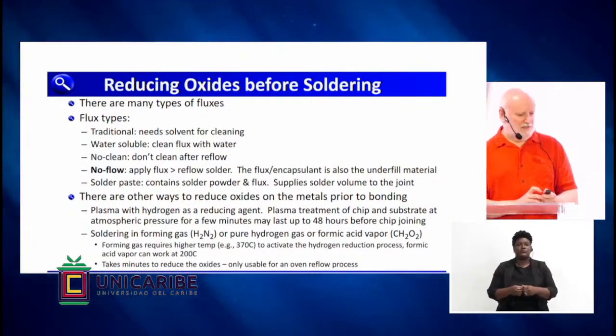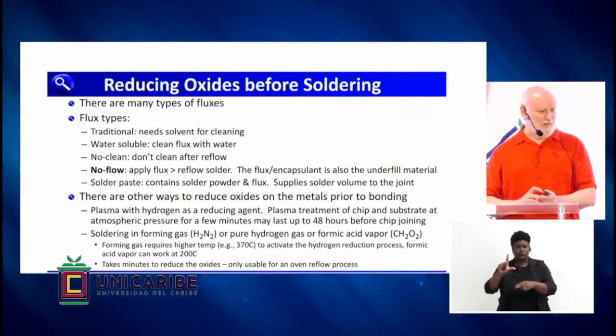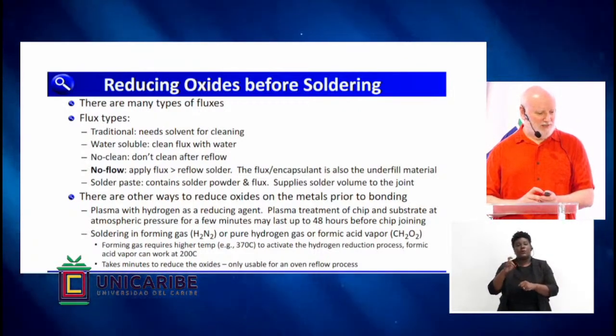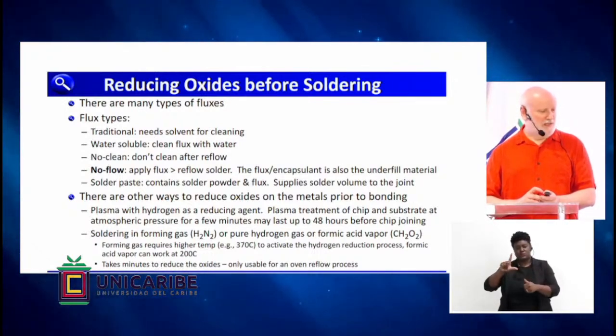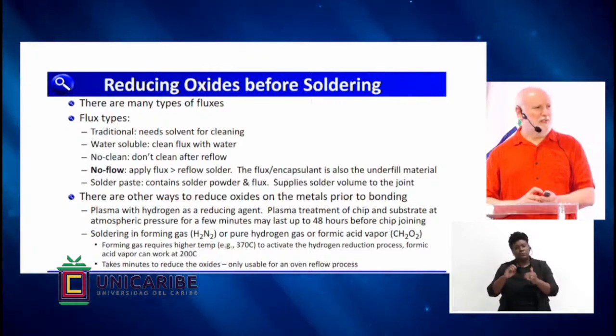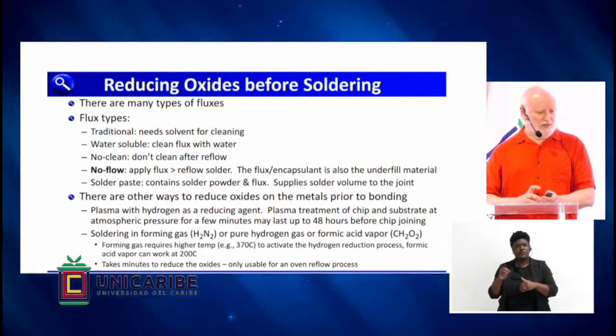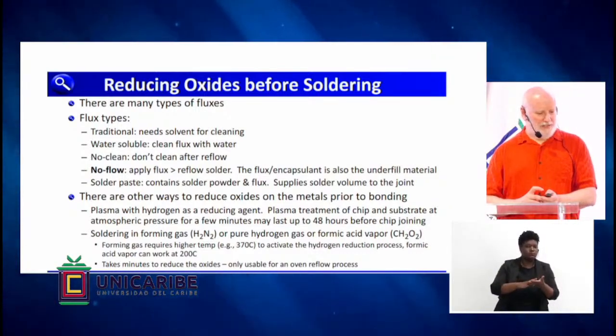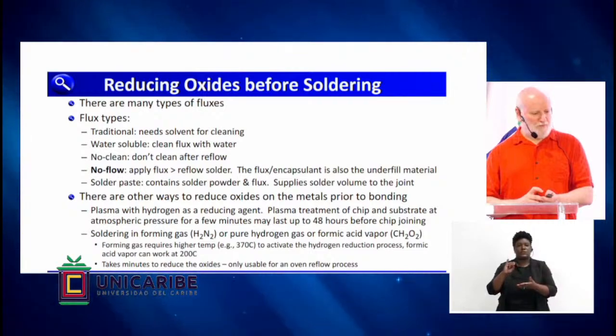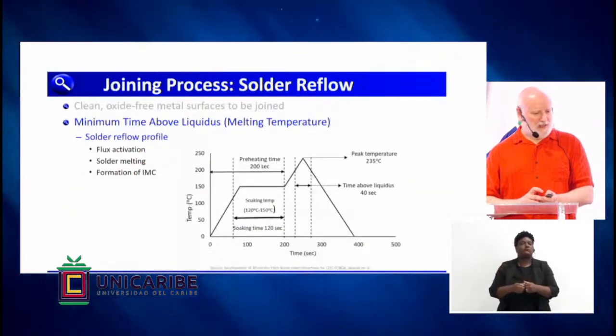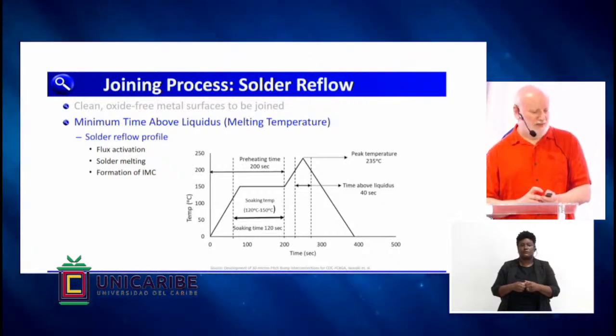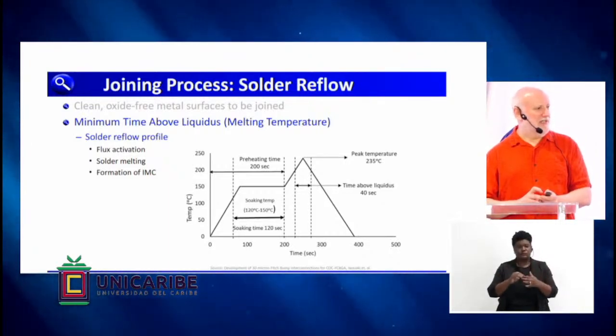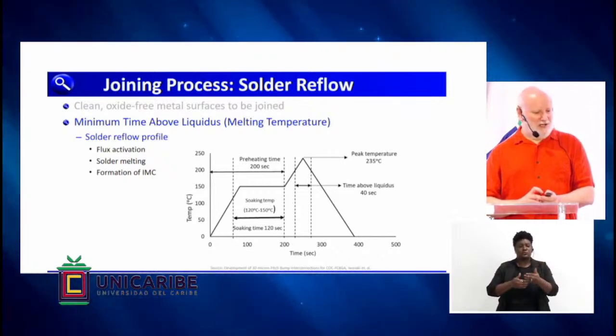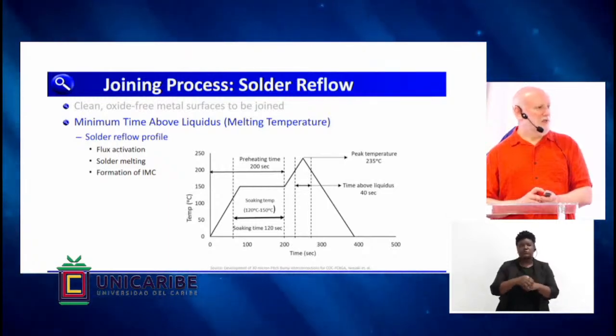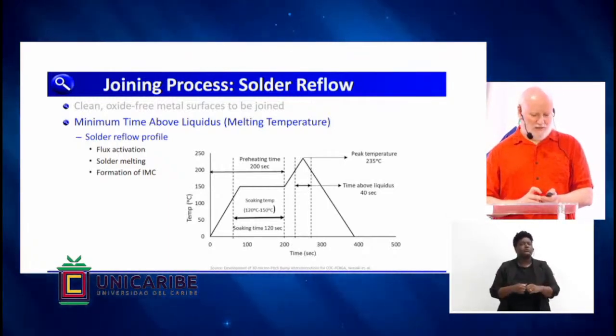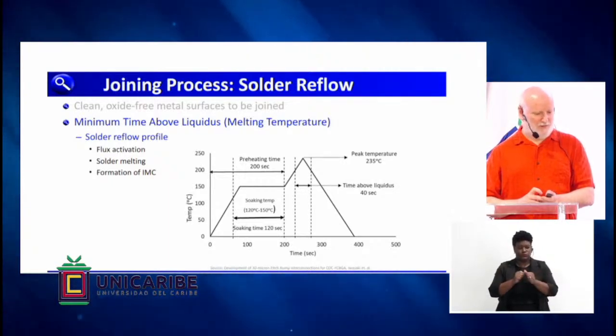You don't have to just use flux. There are other ways to reduce oxides, so you can do plasma processing to reduce the oxides prior to doing the joining. You have a limitation in time between when you do that kind of process and when you do the joining. Or you could solder in something called a forming gas or formic acid. I won't go into all the detail here, but there's a prescribed way to go through a soldering process: a preheat and a soak time, and then you want to reach your reflow temperature, but then cool as quickly as you can. And this is all very well thought out, how to do these processes.